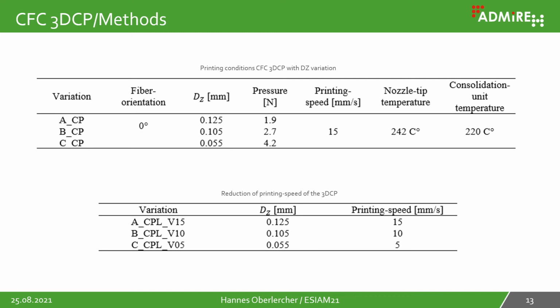In the second experiment, we also reduced the layer height, but also reduced the printing speed. With this experiment, we analyzed the heat transfer into the material, and after that took a closer look at the microstructure, especially the bonding zone of the printed laminate.